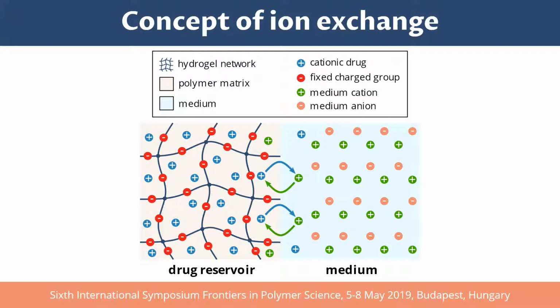Let us talk about the concept of ion exchange. Ion exchange is a charge-selective transport due to Donnan equilibrium. It is enabled by the existence of fixed charge groups along the polymer chain. The illustration here corresponds more precisely to cation exchange, where fixed groups in the hydrogel network are negatively charged. Cations of the drug are exchanged with the cations of the medium, and the drug is released from the reservoir to the medium. This process is driven by the concentration gradient of the cationic drug between the reservoir and the surrounding medium. The process also depends on other parameters, such as pH, ionic strength of the medium, temperature, etc.